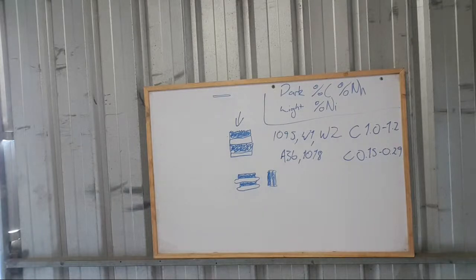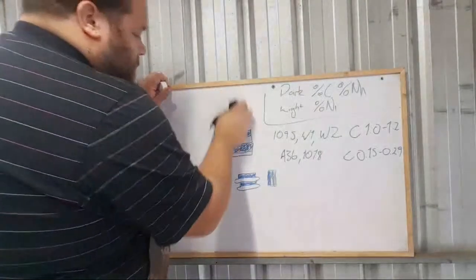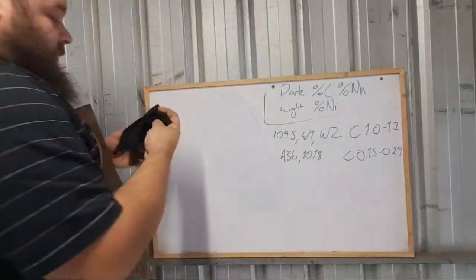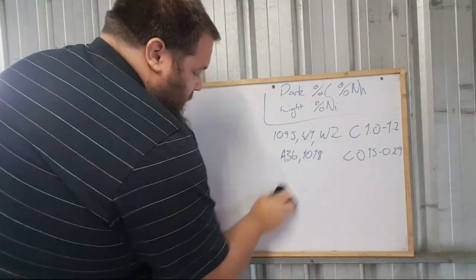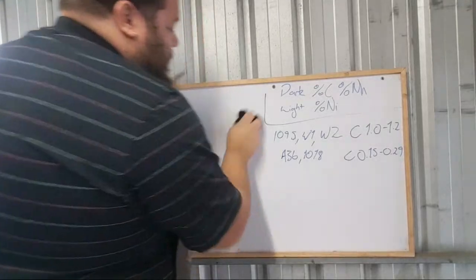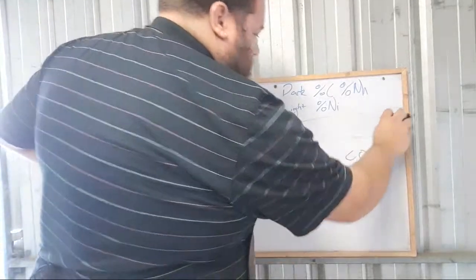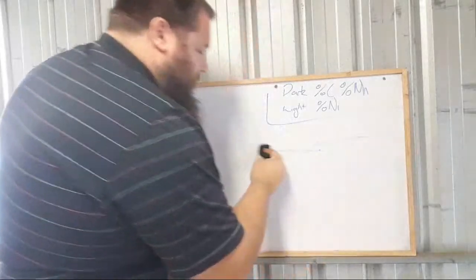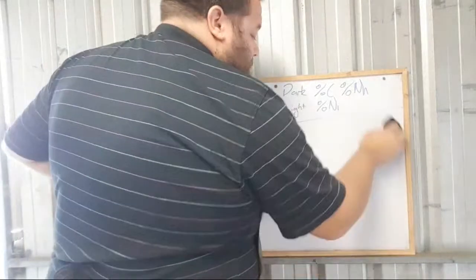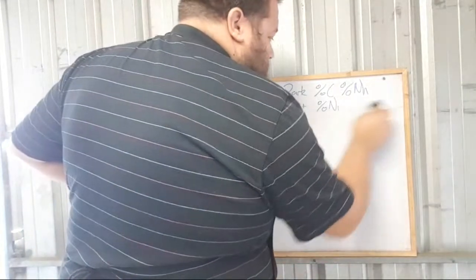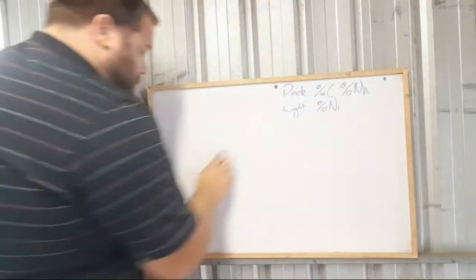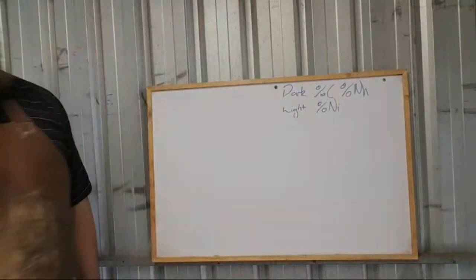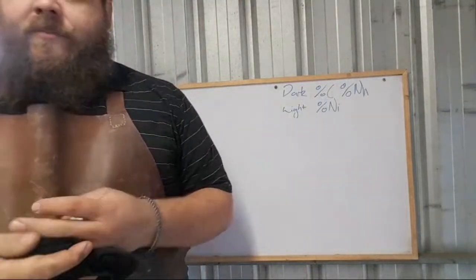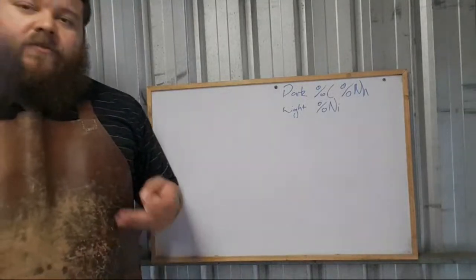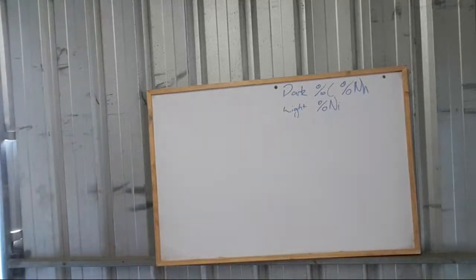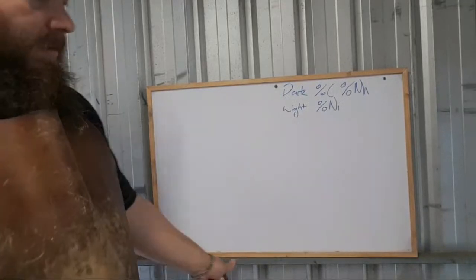So it's important to keep in mind when forging Damascus that you're using chemically similar materials, or if you're not, that they're going to move at very different rates depending on their carbon content, because the higher the carbon content, the slower they'll move. And the higher the chromium content, the slower they'll move. As my friend Alex recently found out, 52100, because it is relatively high chromium and incredibly high carbon, moves much slower under the hammer than any other steel he's ever worked with. It's seriously hard stuff under the hammer. So it's really important to keep that in mind when you come to forge something. That's why 52100 makes a really good Sanmai, because the central core doesn't move, so it's a lot easier to get the whole thing put together right.